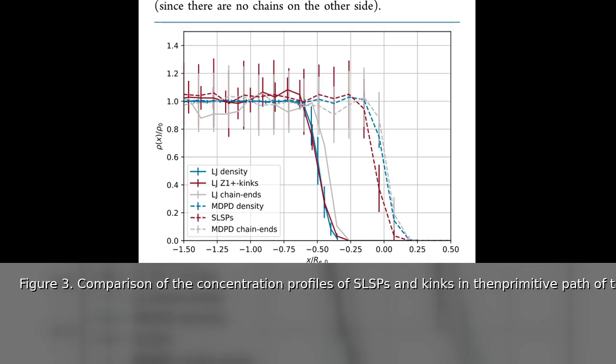This decrease is attributed to the fact that chains residing near the interface have fewer neighboring chains to entangle with, as the vapor phase does not contain polymer chains. Additionally, an enrichment of chain ends near the interface appears in both models, reflecting the decreased entanglement opportunities at boundaries.